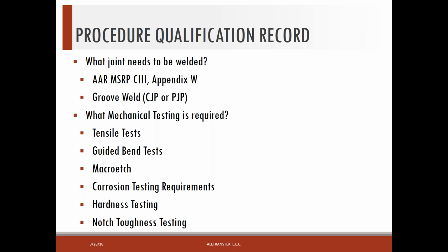Now, if we're looking at pressure car tanks, there are two other things that we have to do. We have to do hardness testing on the heat affected zone and the weld metal, and we also have to do notch toughness testing. That's any pressure car that we might weld on is going to require a weld procedure qualified with notch toughness values.